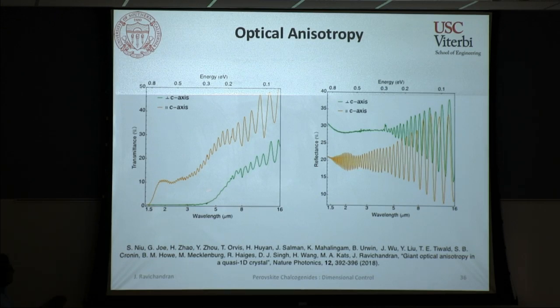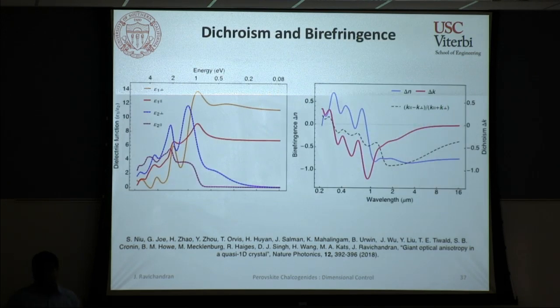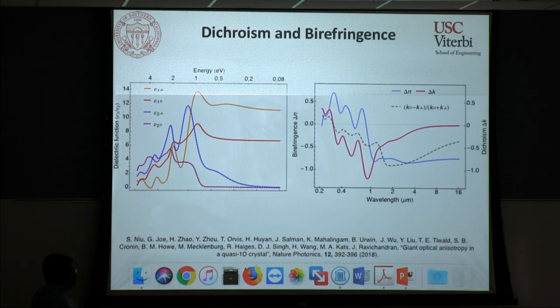So to get the exact optical indices for these materials, we started doing ellipsometry in the absorptive region, which is further to the left of it. And ellipsometry gives you the real and imaginary part of the index, and by combining this data, you should be able to get the whole optical indices for the system over a whole range. So this is a very busy graph on the left. We are showing the absorption edge and the optical indices: the real part, shown in solid lines, along the chain and across the chain, and also the imaginary part along the chain and across the chain.